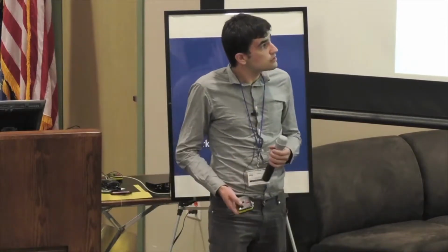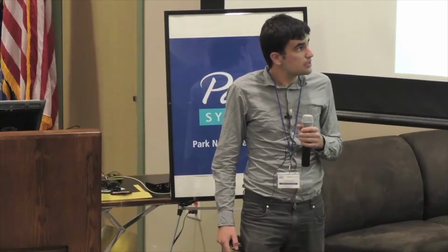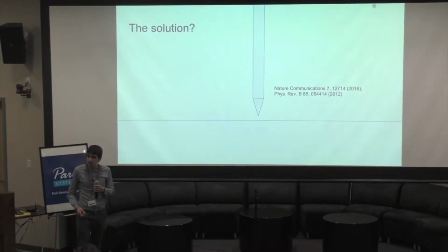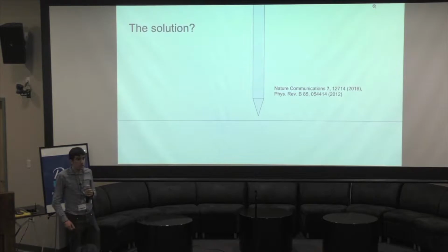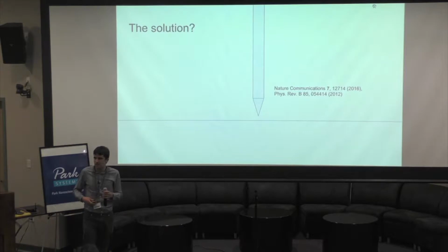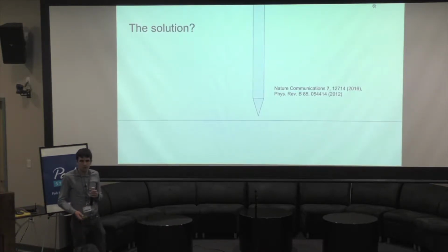And the reason for that is, with the best available devices in the absence of non-contact friction, we would have sufficient sensitivity to see single nuclear spins. So it's an interesting problem to see how to reduce non-contact friction. One thing that's been shown effective in the literature is reducing the area of the tip in proximity to the sample. However, there's only so far you can reduce the size for it to either have a magnetic tip or have a sample attached. So at some point, you have to find some other resolution.